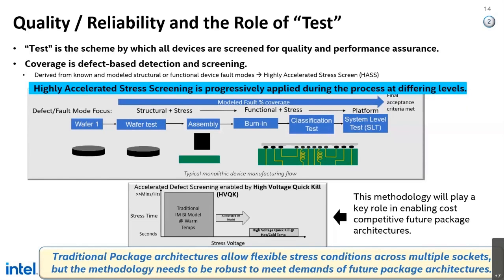So these days, we do stressing at the wafer level with what we call a high voltage quick kill, which is essentially a way to increase the voltage at a wafer level on an individual die level. And we can do it at hot or cold temp, depending on the failure modes we're after, and start the screening from the very beginning. What this is leading to is essentially an interleaved screening process from the very beginning of the metal layers all the way through to package assembly and out into when you have a product.